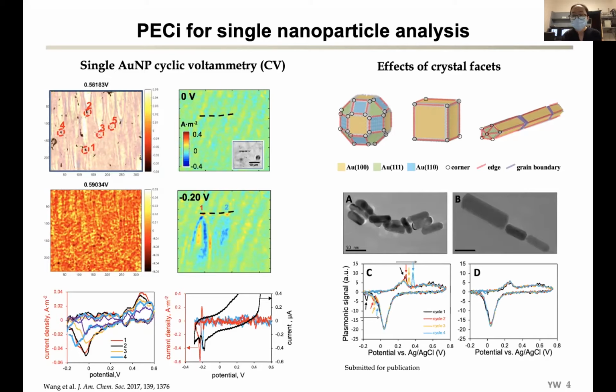And another interesting thing is when we do different cycles, you can see that the position of the peaks is actually drifting during all the 4 cycles, which could suggest that there is a morphological change during the scan. So this is one of the directions where we're still working on.